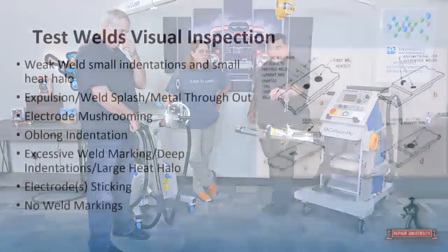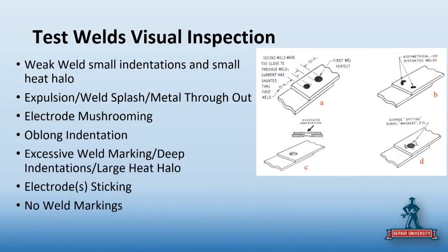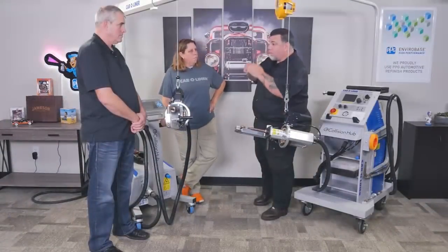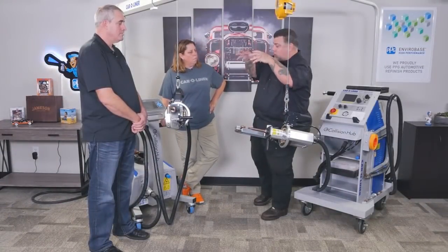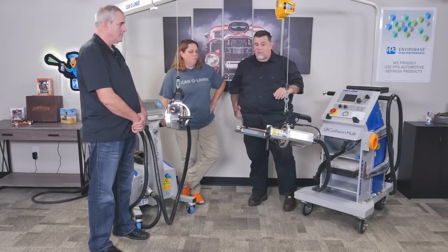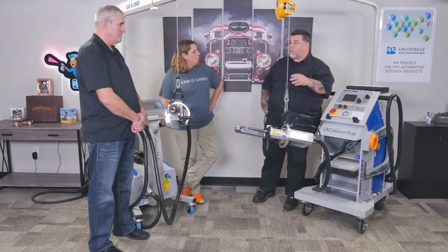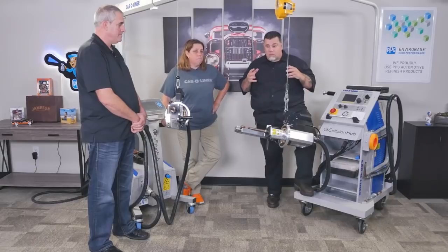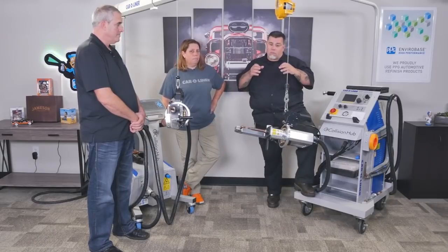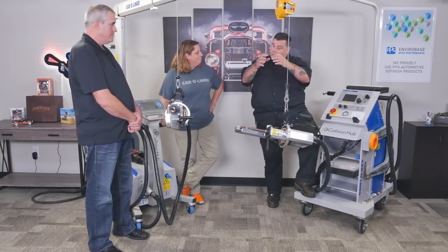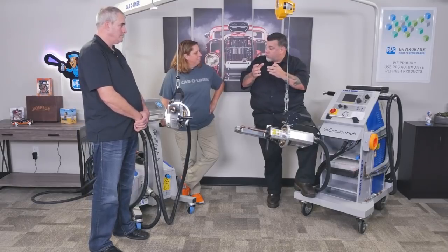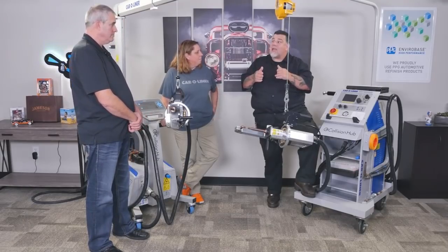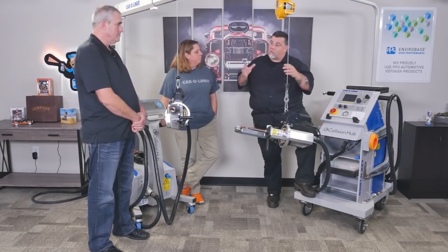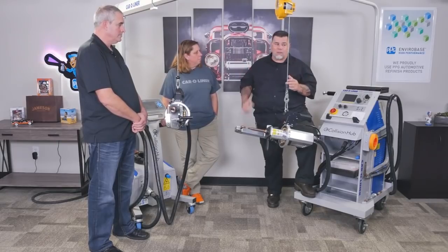Mushrooming. As these tips become worn, the machine, especially auto machines, has to kick up the power, and these tips will start mushrooming and bending backwards, and you get this overlay at the top, almost like a muffin. It looks like a muffin top. And the problem with that is that the bigger the muffin top gets, or the bigger the mushroom protrudes outward, the higher the amperage has to go, because you have a wider contact area.